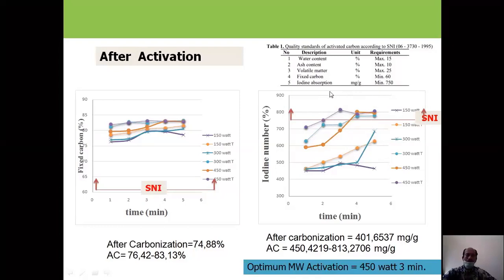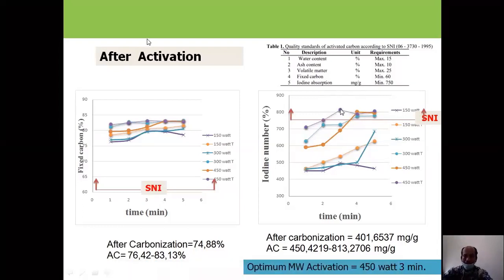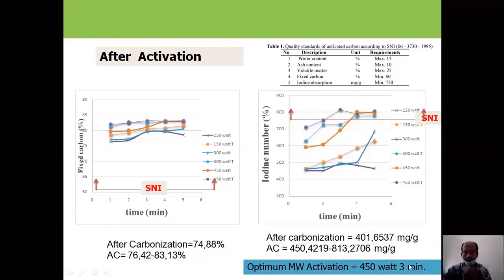So iodine number reflects the adsorption capability of our activated carbon. Some of them are below the expected value, but there are some of them which are above the required value by SNI. For example, this point, then we can say that at this point we have already now the activated carbon needed. Optimum microwave activation happened at 450 watts and 3 minutes irradiation of microwave.